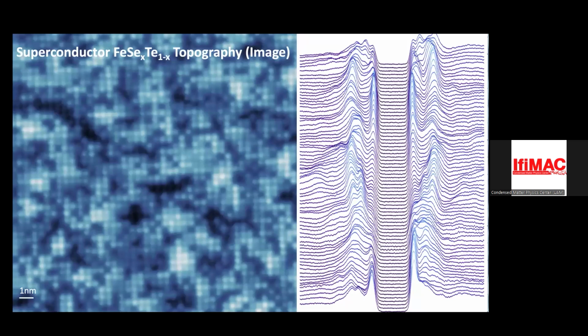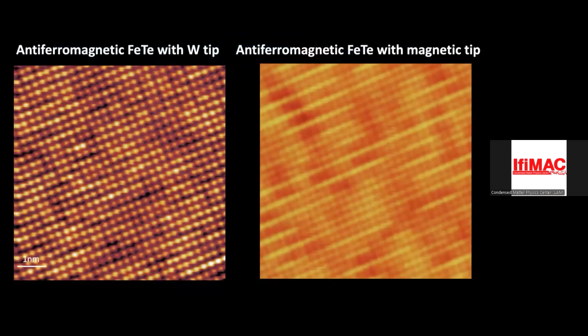Okay, and since you're very familiar with STM, I can go quickly over this. Essentially, this is just to show you how powerful STM is. You can get beautiful images. This is an image of the superconductor FeSe. And now if you add some tellurium to it, it looks like this. The inhomogeneity that you see is electronic. And in fact, this is the superconducting gap. And you can see how the coherence peaks change as a function of position. All this inhomogeneity in the superconducting properties comes from the inhomogeneity in the electronic properties.